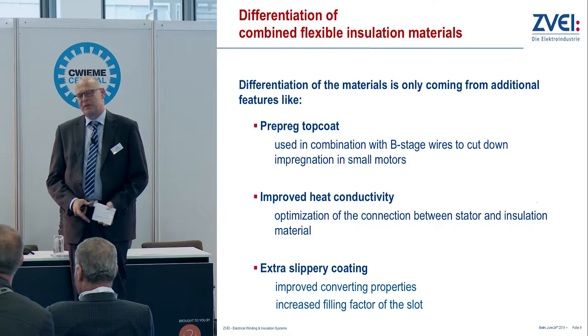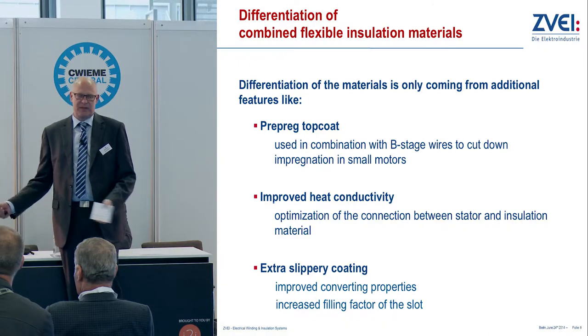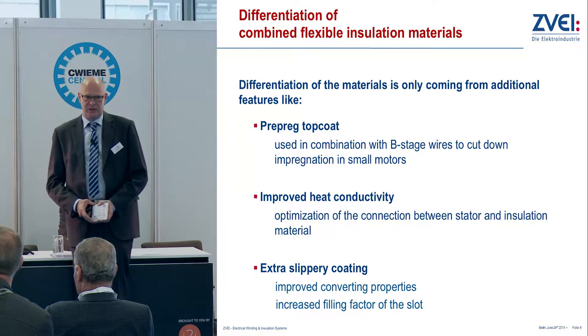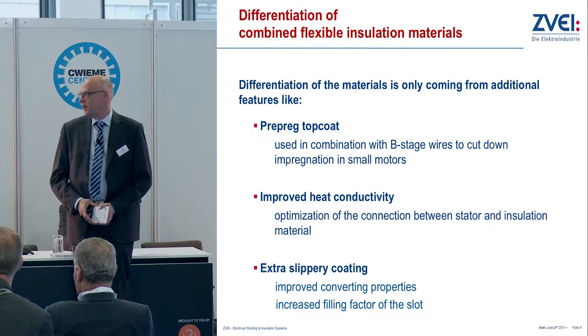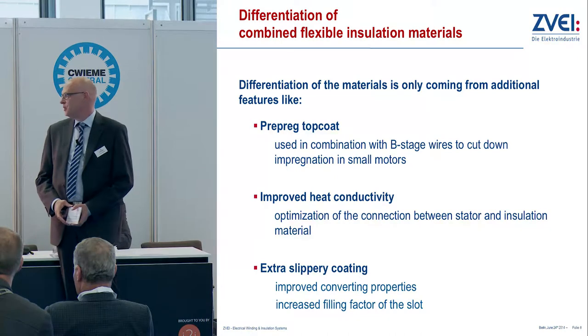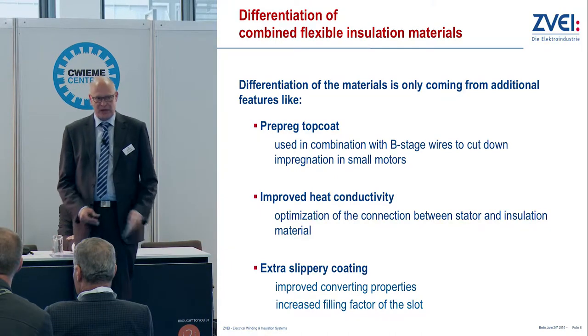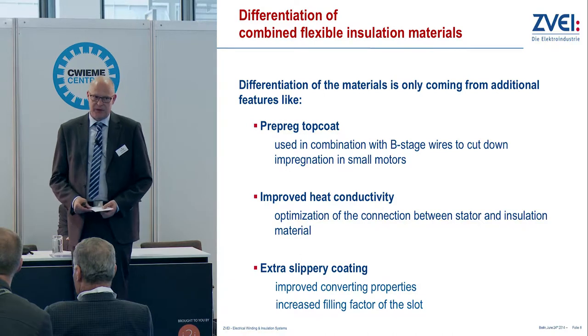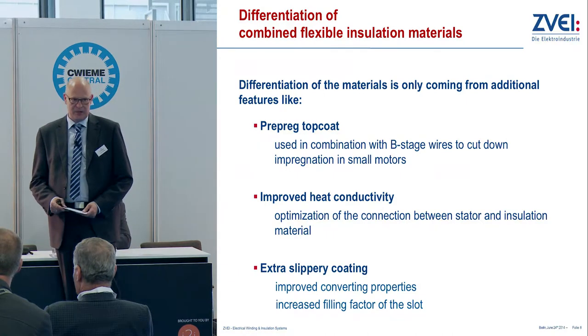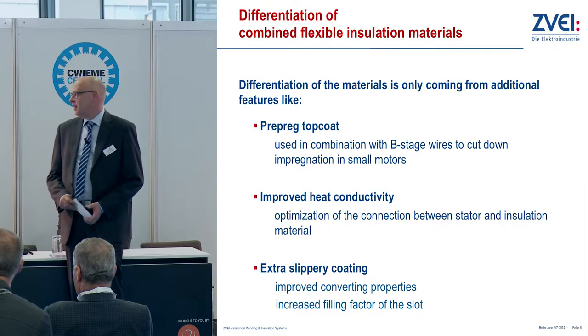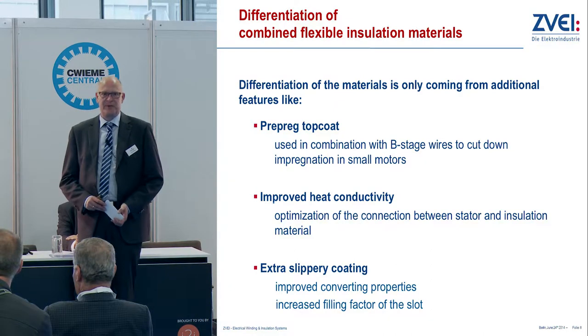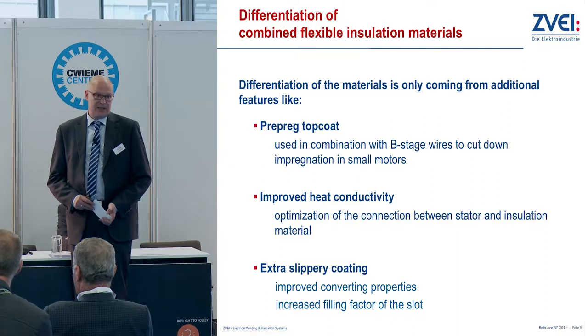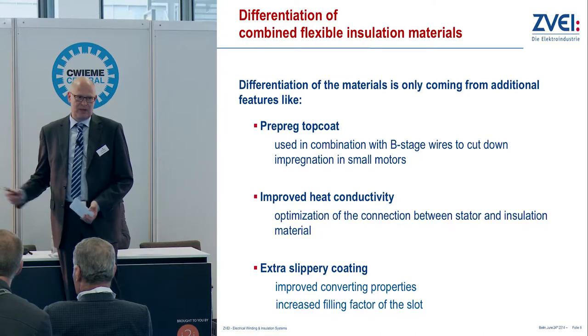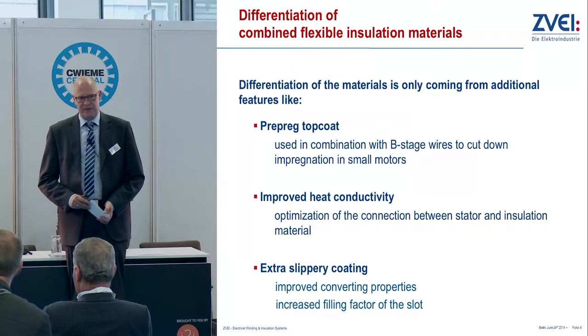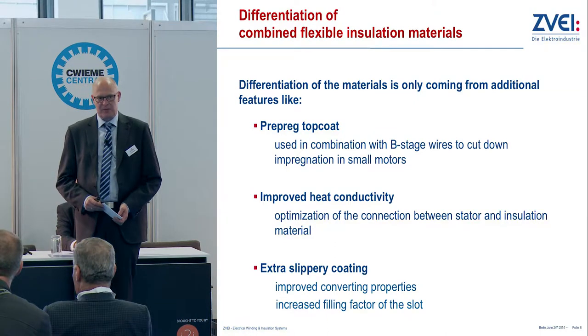So the differentiation of flexible insulating materials from competitors is only done by additional features. For the time being, we have prepreg topcoats used in combination with B-stage wires, so you can avoid an additional trickling or impregnation process of the winding. And then we have some resin systems which are filled to improve the heat conductivity between the stator and the insulating material and respectively the winding. So these are filled coatings which are available already.